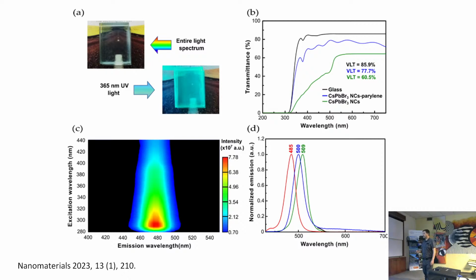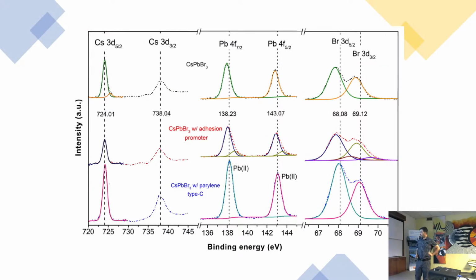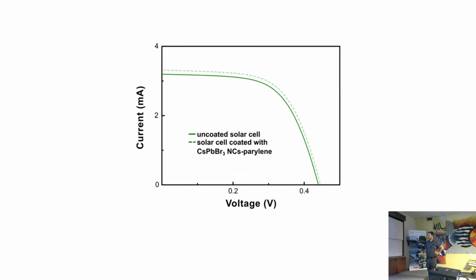Here is the luminescence. In fact, when we do the encapsulation with the parylene, the emission shifted into the blue, but the emission looked quite okay. This is the 3D spectrum. We have excitation and emission spectrum, but in here you have the emission spectrum, and the transparency of the material was good. So we did also XPS. I'm going to jump this part. In the end, we could check that the efficiency of the solar cell indeed improved when we put the quantum dots with the parylene coating. Still not a luminescent solar concentrator. Okay?